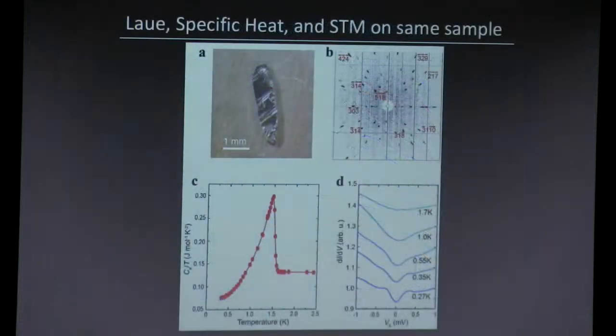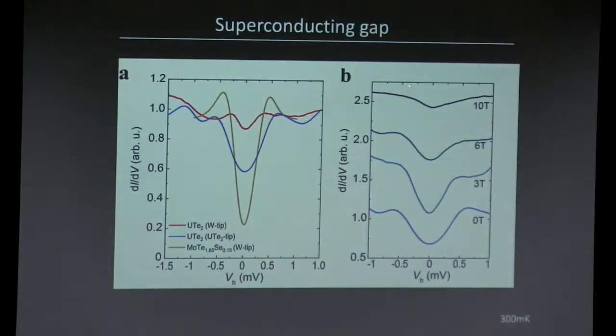So we can do temperature dependence, and the gap goes away at the right temperature. We can do magnetic field dependence, and the gap disappears close to Hc2. It's almost gone at 10 Tesla, that's our largest field, and 11 or 12 Tesla is the Hc2 in this direction. So based on the suppression with temperature and magnetic field, this very, very shallow gap is the superconducting gap in this system.